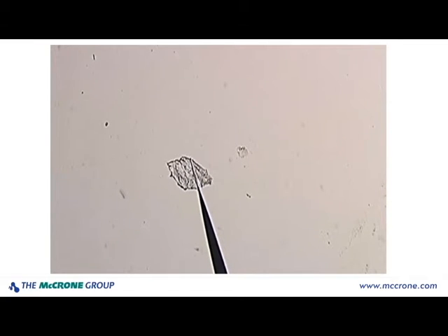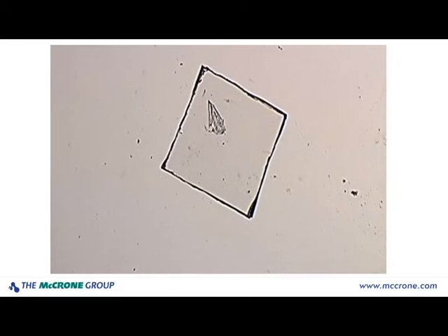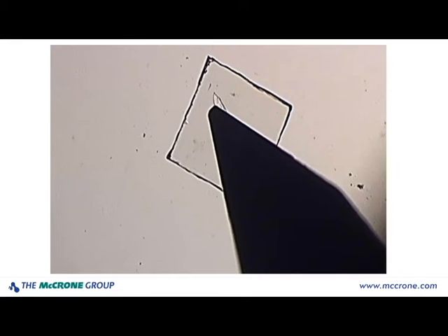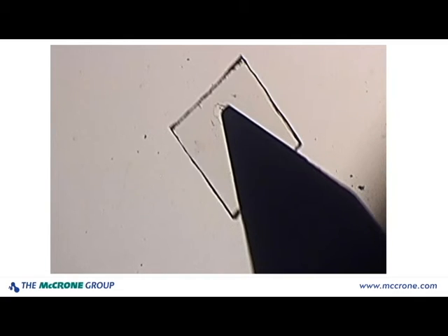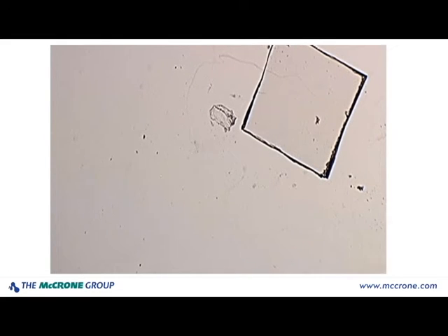Some polymers, you'll have to cut smaller pieces from your flattened piece, which I'm doing here with my tungsten needle, which actually is giving me a little bit of a difficulty. So I'm going to switch to my 45-degree microblade. I'm then going to press it again with the micro cover glass, so my piece is actually thin enough to obtain a spectra. Now this thin piece can then be transferred to the micro KBr with my tungsten needle.